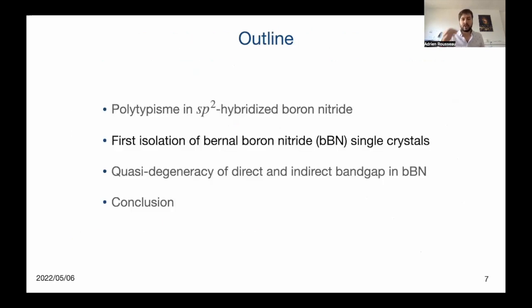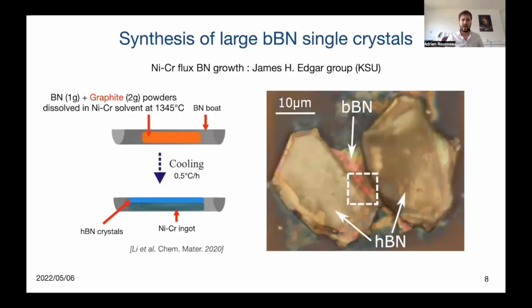Now I will present you a result on the first isolation of a Bernal boron nitride single crystal using optical techniques. Our sample has been provided by our collaborator from the Kansas State University, and has been fabricated using the nickel chromium flux method for growing hexagonal boron nitride, which has been doped with carbon by adding a graphite powder inside the nickel chromium solvent, as represented on the scheme on the left.